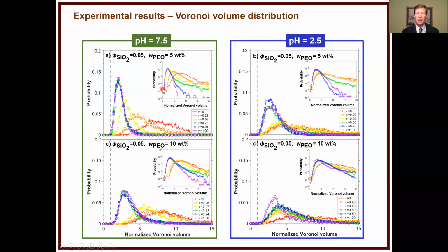Now, I also have to remind you that we have something between a few thousand and 10,000 particles in each scan, and then we average over many scans, right? And so just to think about this probability, down below about 10 to the third, all this noise back here and down here at this end of the tail, essentially what that's telling you is it is truly noise. We don't have statistical representation. What we can do is fit these curves for everything above about, I think it was something like 2 or 5 times 10 to the minus 3, and just fit the rounded tops of those.